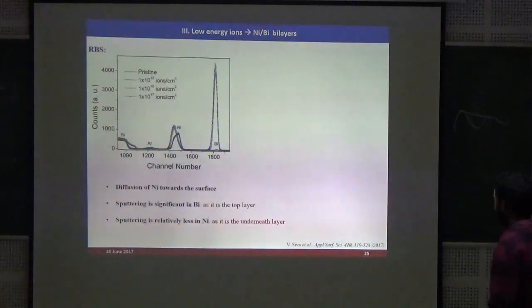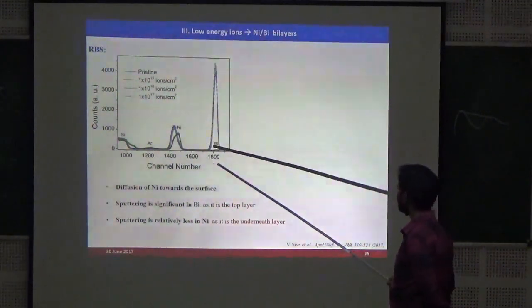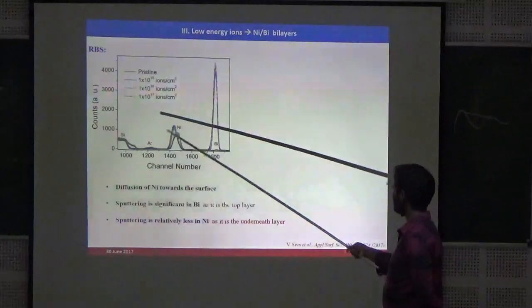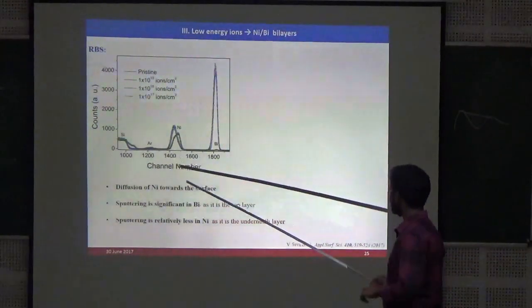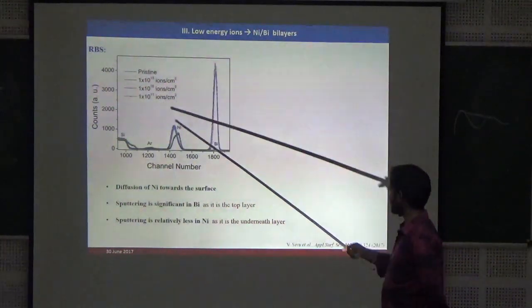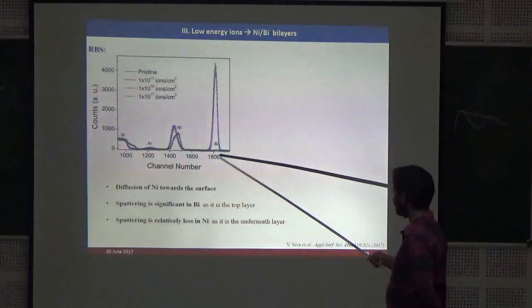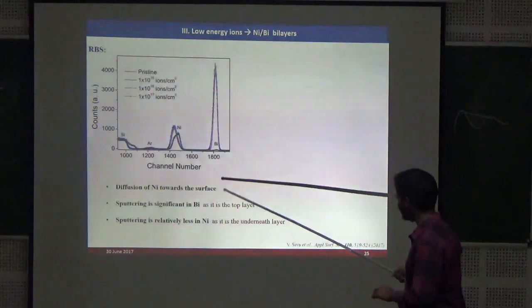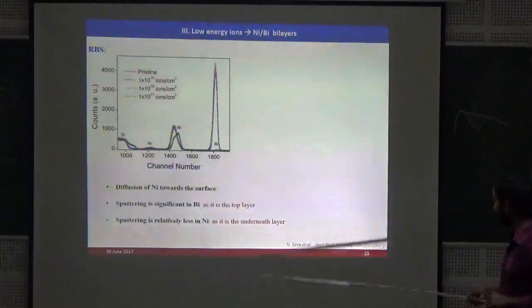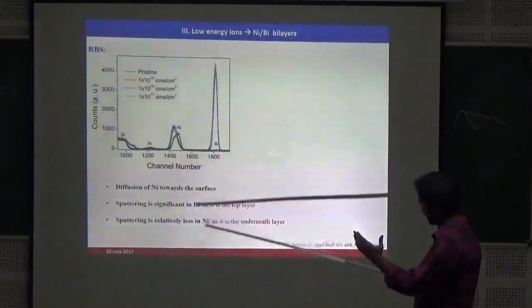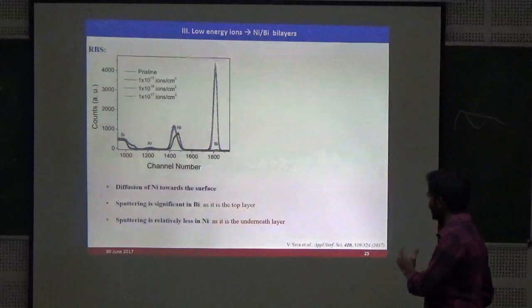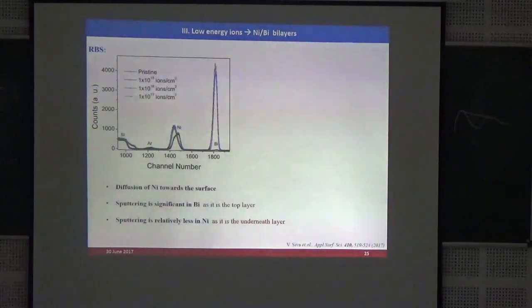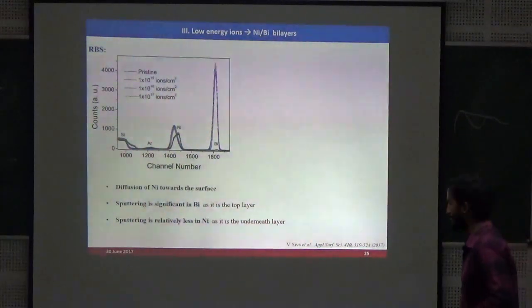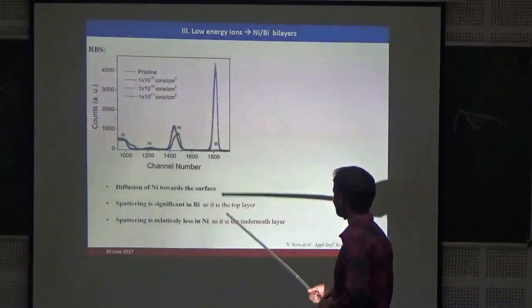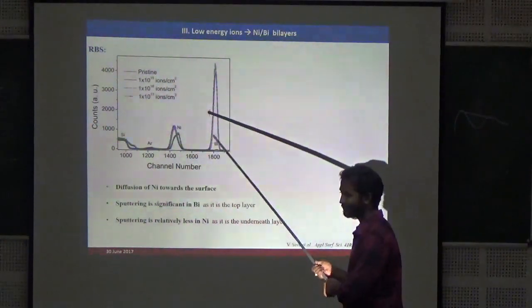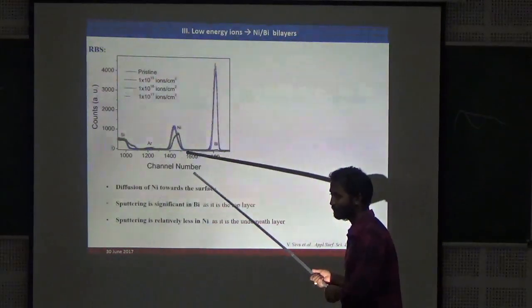So here you can see this is RBS data where you can see the nickel and silicon peaks. At the highest fluence case, the bismuth layer is almost not there. That means it is sputtered out, the whole layer. And the nickel is trying to move towards the higher energy side. That means there is a mixing in this case. These open symbols are simulations? No, everything is actually experimental results, for different fluences.